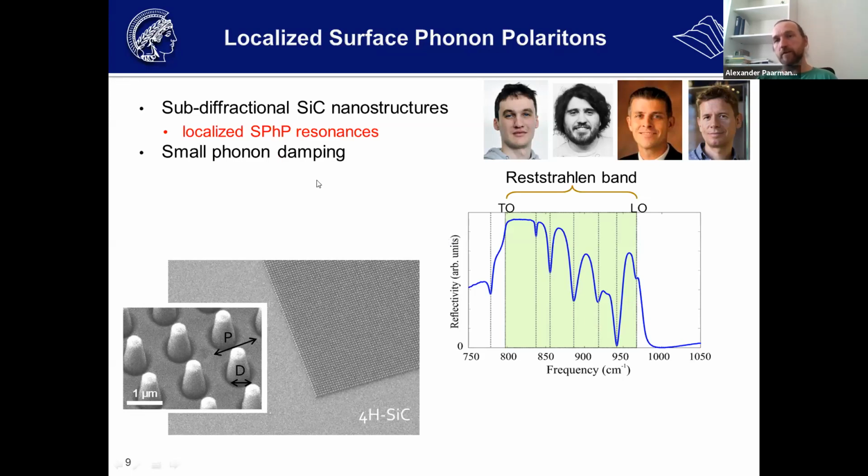This is really a big difference to most plasmonic systems, because in plasmonics, typically the Q factors of these resonances are much smaller. I had looked at plasmonic systems and tried to find good systems for our spectroscopy, but this really popped up as a very important point. The main difference here is really that because of the long lifetimes of these optical phonons in comparison to plasmons, the damping is small. This is what makes the Q factors of the resonances so large. And this is really also what triggered this whole field of phonon polaritonics.